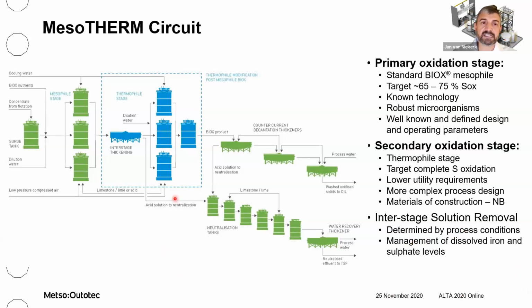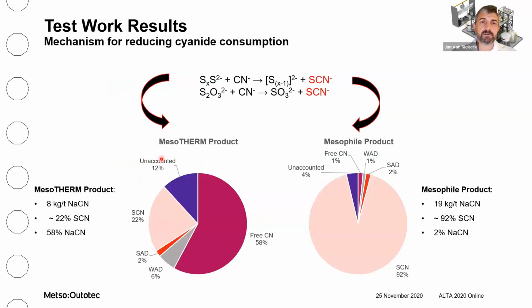We also include an interstage thickening step to manage the dissolved iron and sulfate levels in the feed to the thermophile stage. And what we're trying to achieve is to reduce or eliminate any intermediate sulfur species that can be typically found in a mesophile BIOX product. These intermediate or partially oxidized sulfur species can react with cyanide to form thiocyanate and therefore increase your overall cyanide consumption.